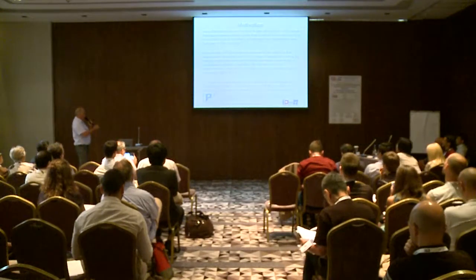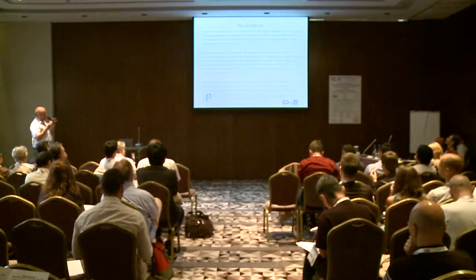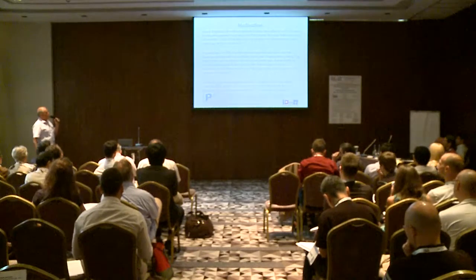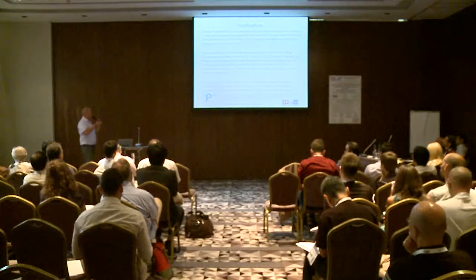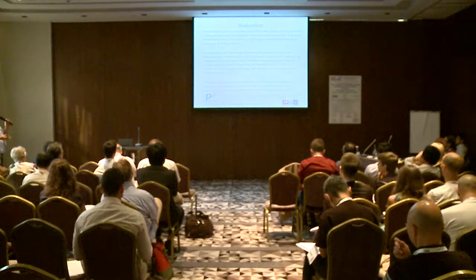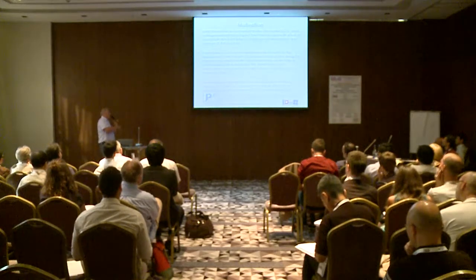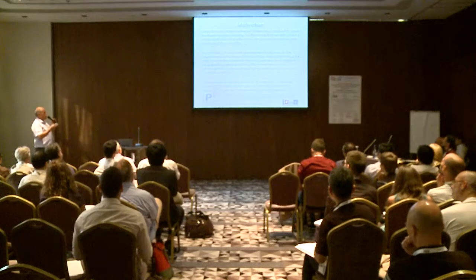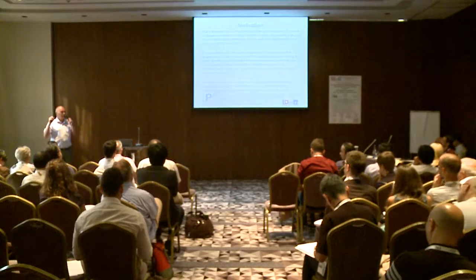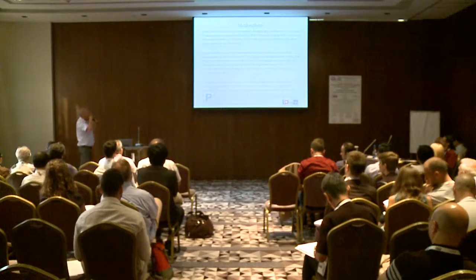As more particularly concerns the motivation of the work I will present today, a couple of years ago we developed a model based on cohesive zone models coupled with diffusion equations, in order to try to predict the fatigue crack growth enhancement observed under high pressure of gaseous hydrogen in martensitic steels. The point is that we were unable to reproduce the tremendous fatigue crack growth enhancement that we experimentally observed. One of the conclusions was that in this model we do not introduce any effect of hydrogen on the local plasticity at the crack tip, and the reason is that at that time we had no information about this.